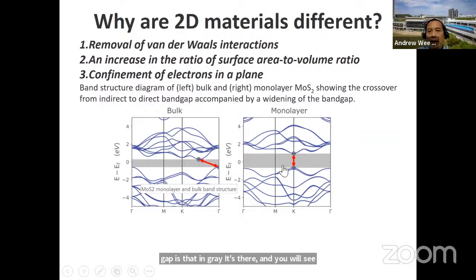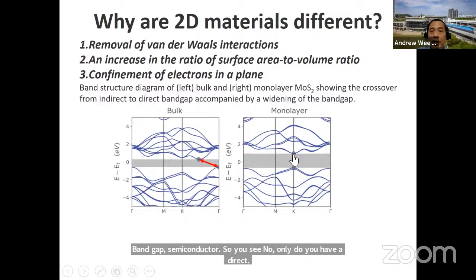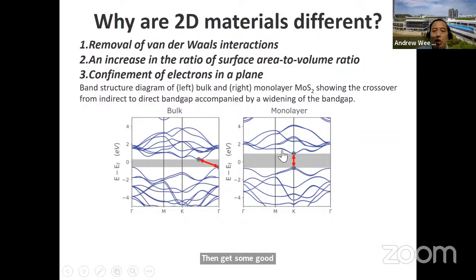Whereas in the monolayer, the maximum of the valence band is directly below the minimum of the conduction band. So you have a direct band gap semiconductor. So you see, not only do you have a direct band gap semiconductor, you have a widening of the band gap as well.